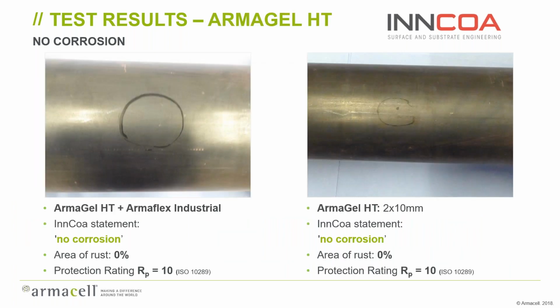Two different ArmaGel installations were also observed, one with ArmaGel and a layer of ArmaFlex flexible elastomeric foam over the top, and on the right, just with ArmaGel, 2 layers of ArmaGel. Just in passing, the circle on all those samples represents where a hole was introduced into the insulation system. In both cases here, Incoa said no corrosion, 0% rust, and a protection rating of 10. That's phenomenal. We were both surprised and very delighted to see the degree of protection.